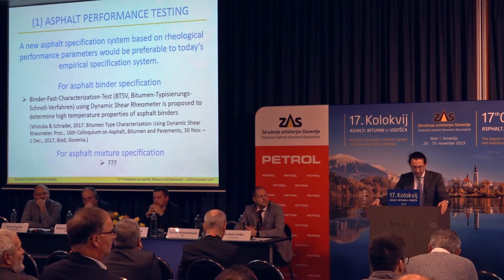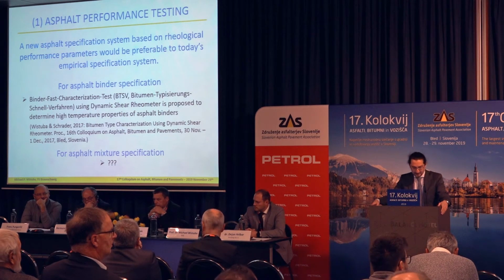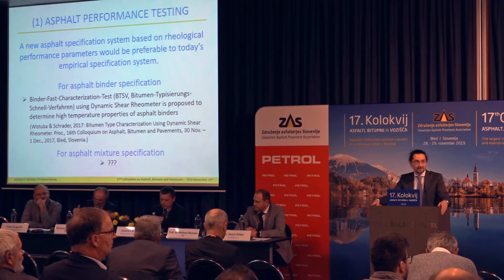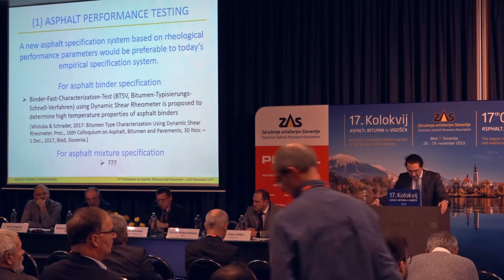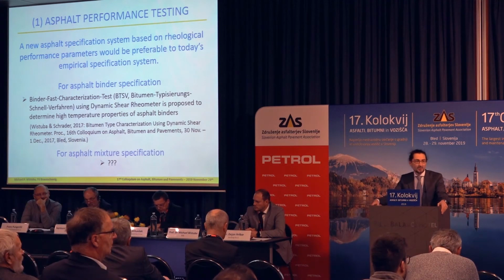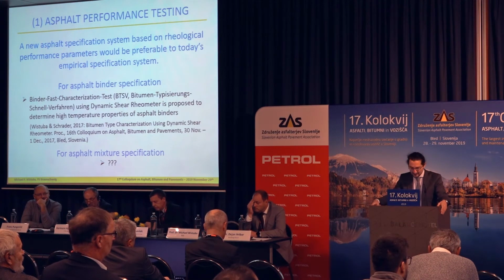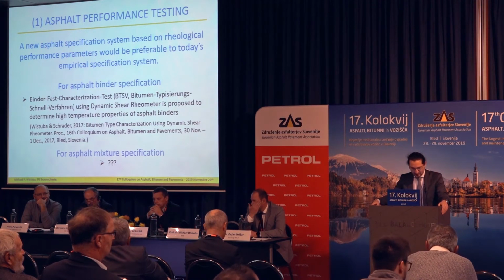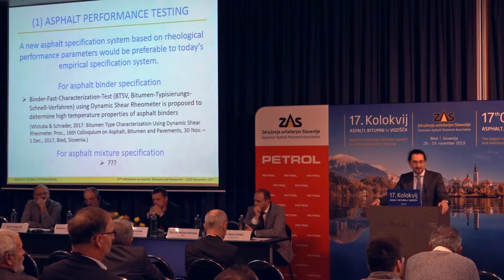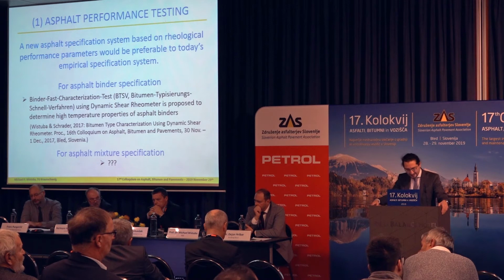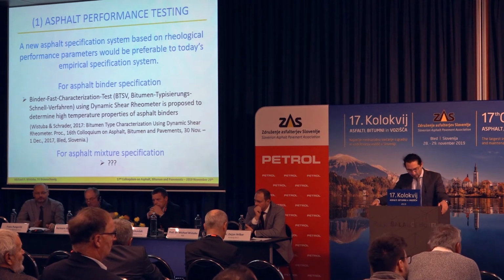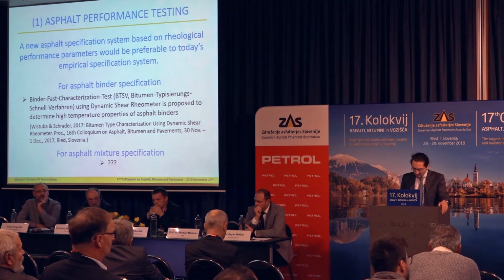And our first approach to this problem was more or less the development of the binder fast characterization test, which was presented 2 years ago, also here in Bled. And this is the first step, which is a nice parameter to check the quality of bitumen and the performance of bitumen in the moderate and high temperature range. So what about asphalt mixture specification? How can we predict asphalt mixture properties in the laboratory at low cost and in low time?